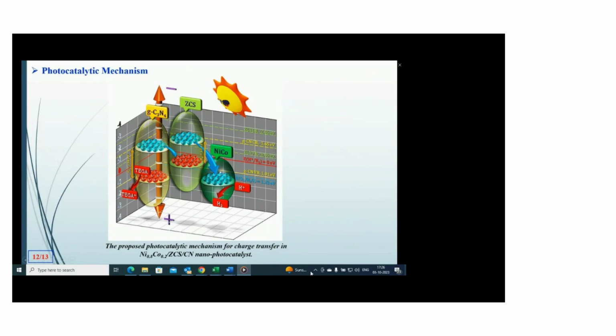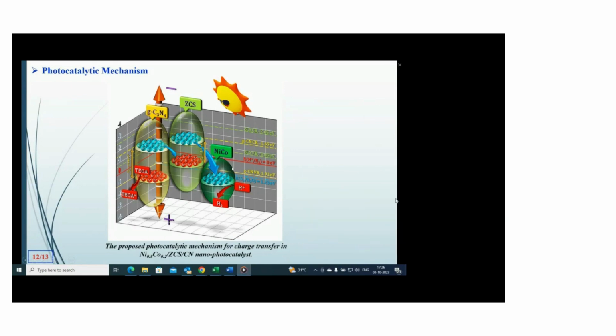A Schottky junction is formed between ZnCdS and nickel cobalt nanoparticles due to the difference in their work function, and the conduction band electrons of ZnCdS prefer to transfer to the NiCo nanoparticles. These nanoparticles serve as electron traps, and this electron transfer reduces charge carrier recombination. And according to the figure, the electrons on NiCo nanoparticles and the holes on the valence band of g-C3N4 participate in the reduction and oxidation reactions, respectively. This mechanism enhances dispersion and utilization of photogenerated charge carriers, leading to enhanced photocatalytic efficiency and effectiveness for hydrogen production.